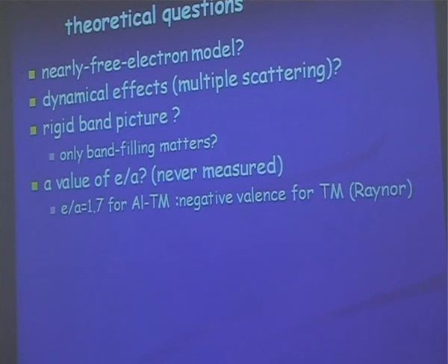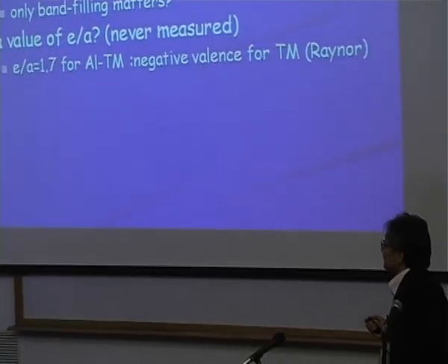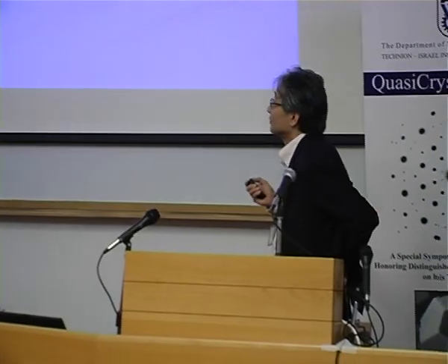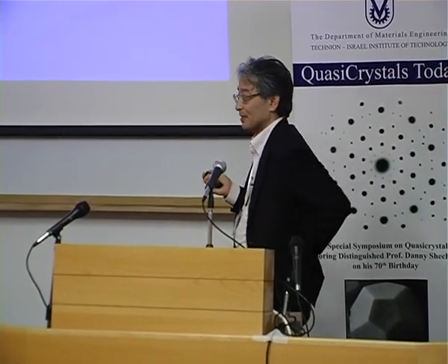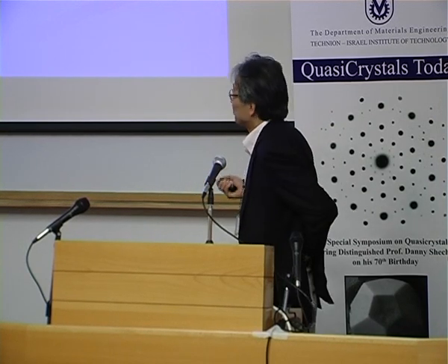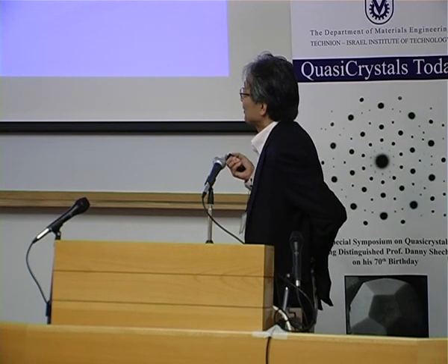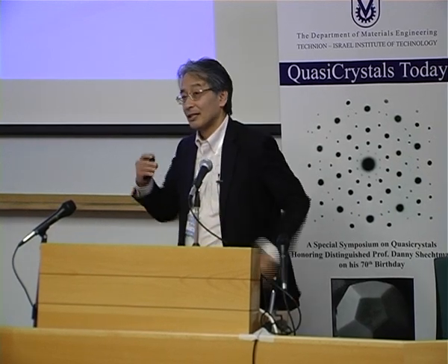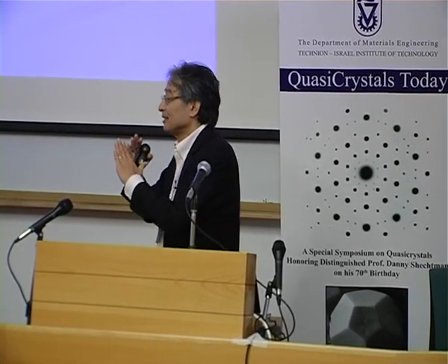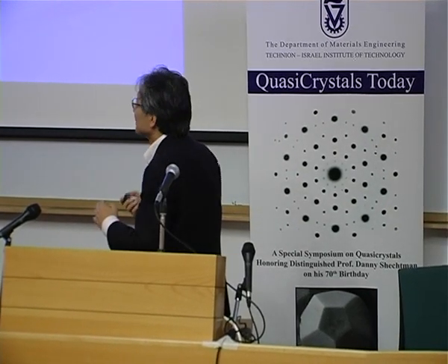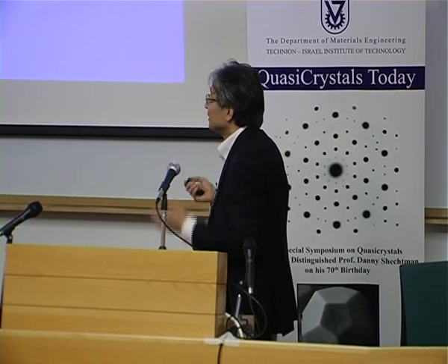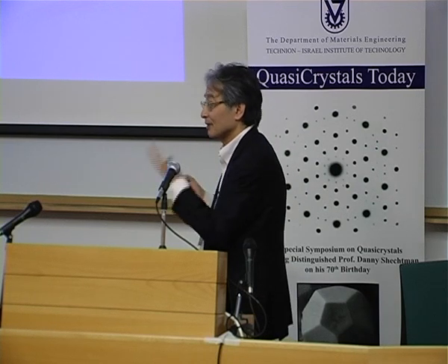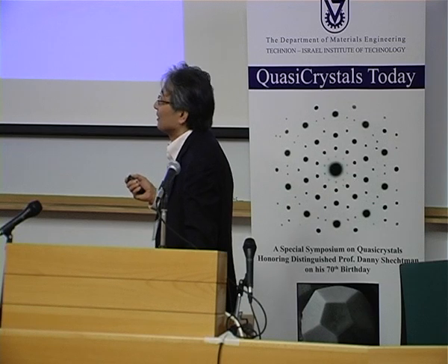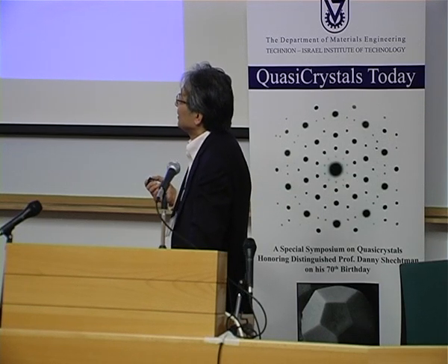But I think there are a lot of theoretical questions about such simple descriptions. First, we start from the nearly free electron model. So we should check if the nearly free electron model is correct enough for the aluminum transition metal alloys, because the transition metal should scatter the electrons more strongly. Also, I showed the gap opening at the zone boundary by two-wave mixing. But in condensed matter, we usually have to include the effect of multiple scattering to describe the electronic structure more correctly. So we should check the dynamical effect. And also the rigid band picture should be checked more carefully.